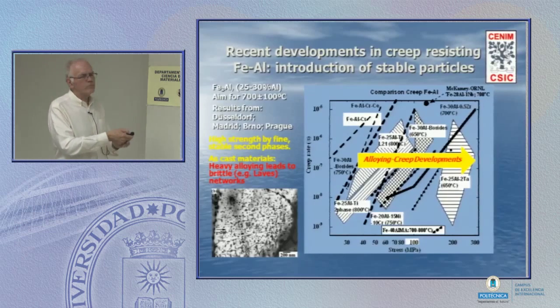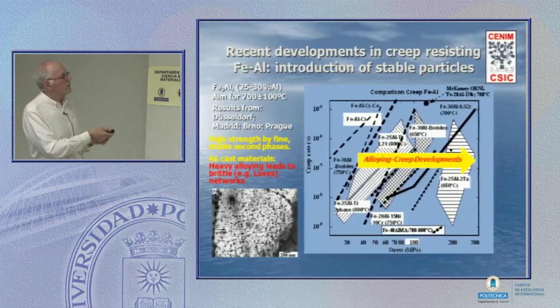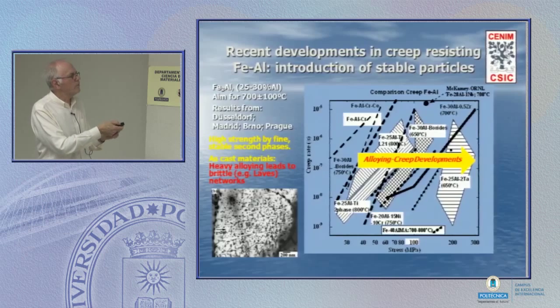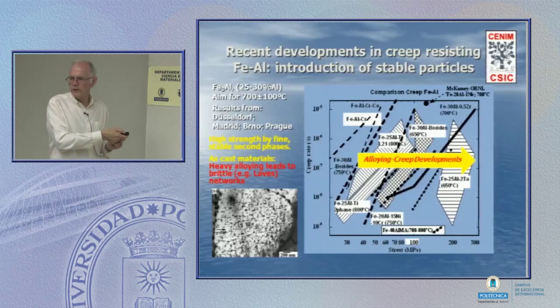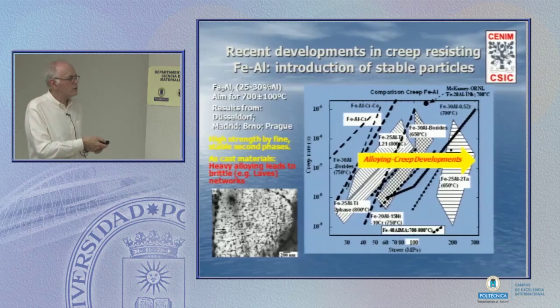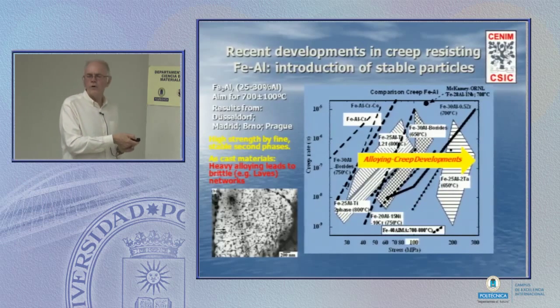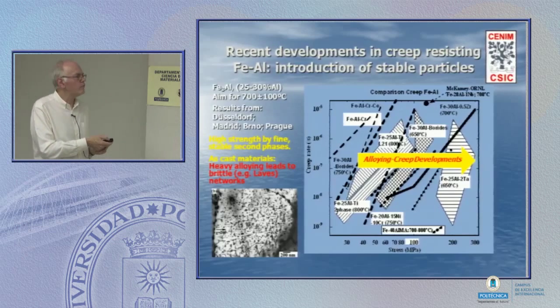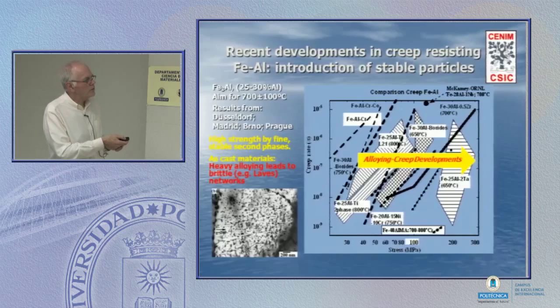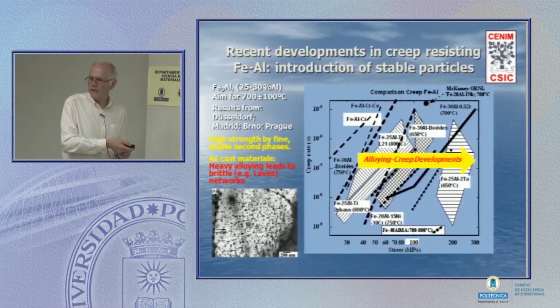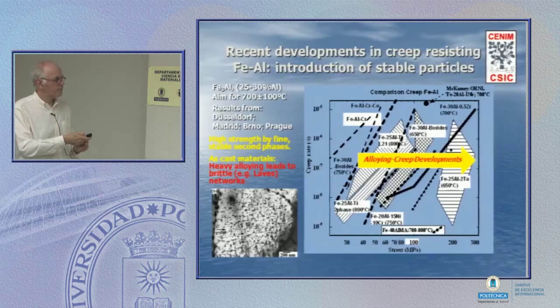And you see here in this messy graph on the right, this is the creep rate for a given applied stress at 700 Celsius. This is the stress that we can apply for these creep rates in the binary iron aluminide, or binary iron aluminide adding chromium. No strengthening particles. If we add titanium that forms particles, or boron, or nickel, or tantalum, or zirconium, all of these form second phase particles of different types that have better and better stability. And so the strength has been improved by 1 order of magnitude over the last about 10 years.